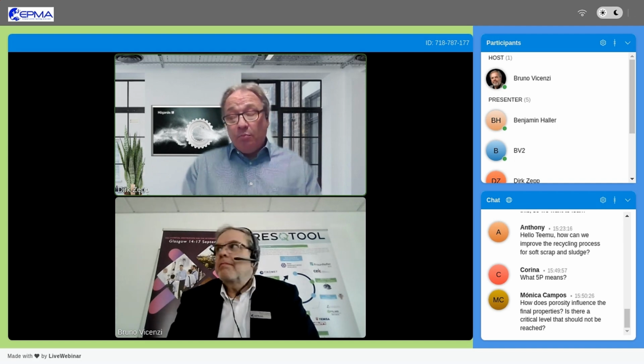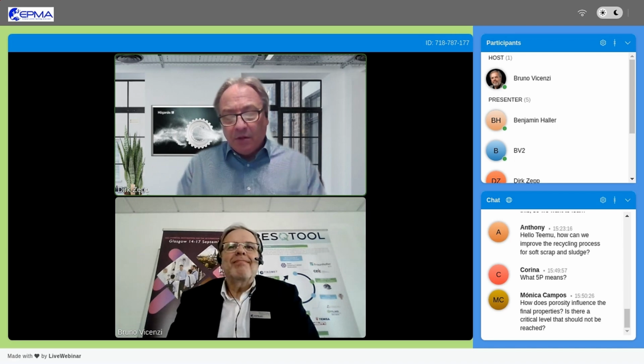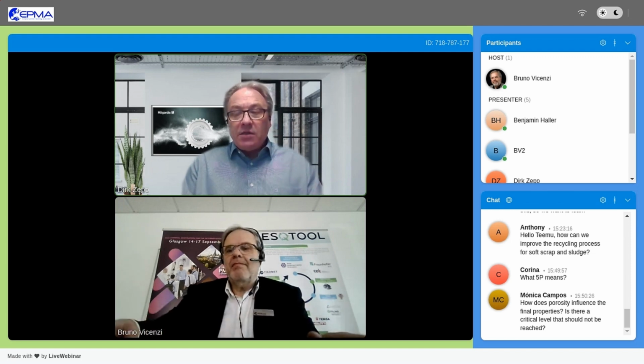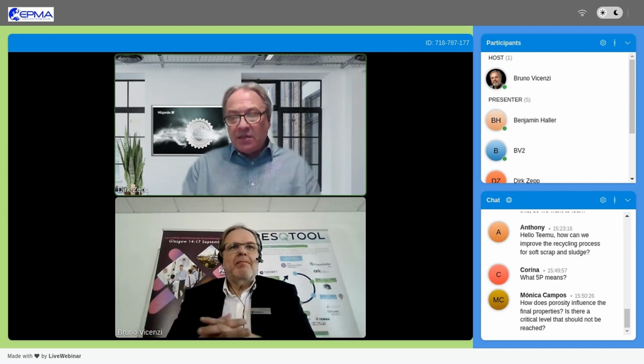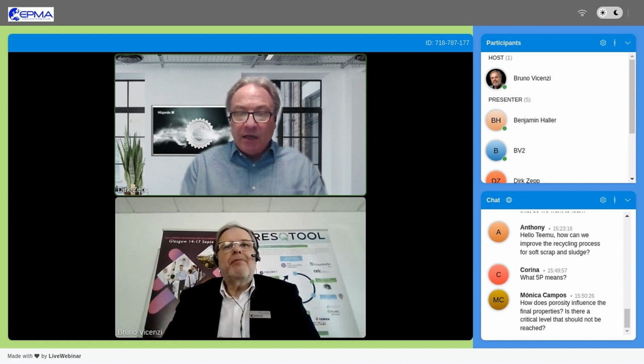The mechanical strength is of course a certain issue. Absolutely, because the mechanical strength due to the manufacturing process is lower than if you have something made out of a block of iron. Absolutely. But still, we measure the mechanical strength in TRS, so it's a 3-point bending, because if you do a normal tear test, already the mounting in the machine could damage the test sample. Yeah. But we see also here improvement for the future to get higher strengths.